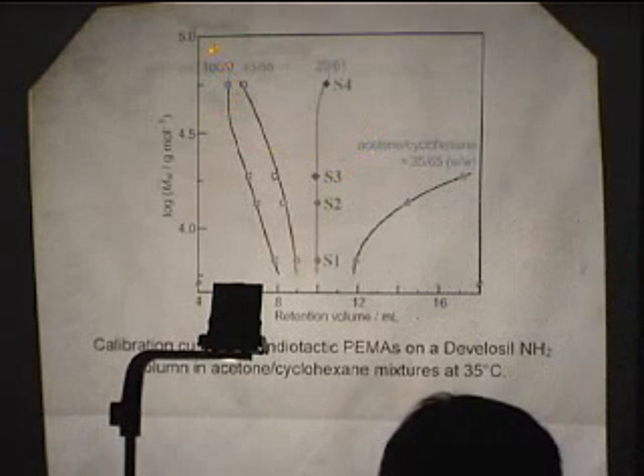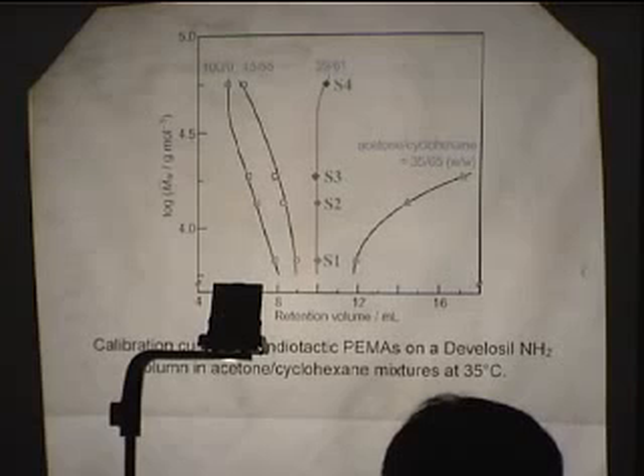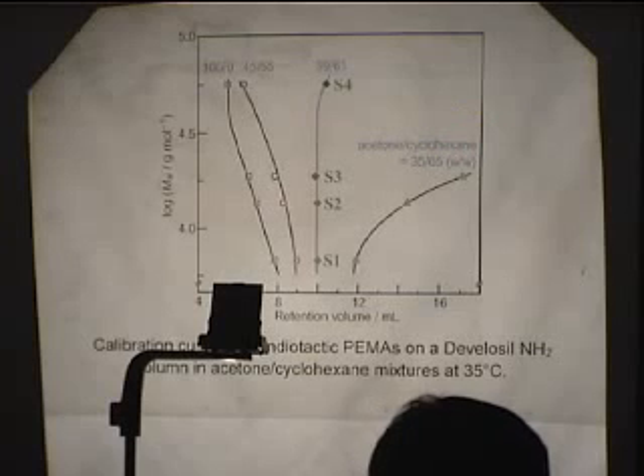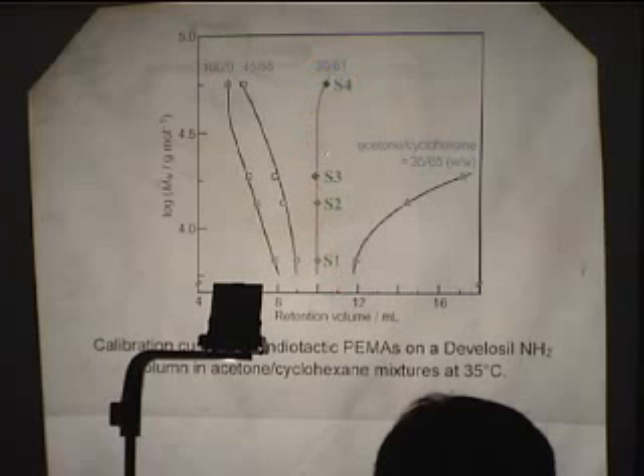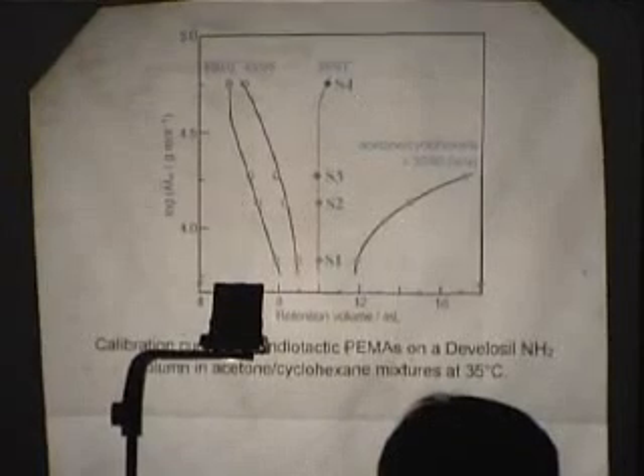When this polymer, the highly syndiotactic PMMA, was eluted in acetone, it eluted in the size exclusion mode, as shown. When cyclohexane was added to the eluent, the elution behavior changed to adsorption. And you can see that at a composition of 39 to 61, we found critical adsorption conditions for highly syndiotactic PMMA. This is because acetone is a good solvent for PMMA, whereas cyclohexane is a poor solvent. Under these conditions, polymers with lower syndiotacticity still elute in non-critical conditions, so the discrimination of tacticity is achieved.